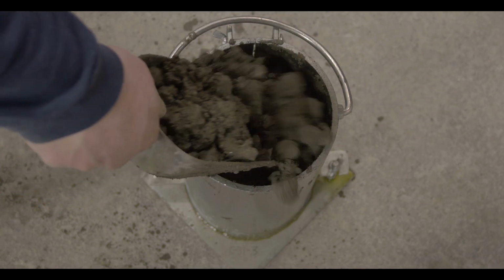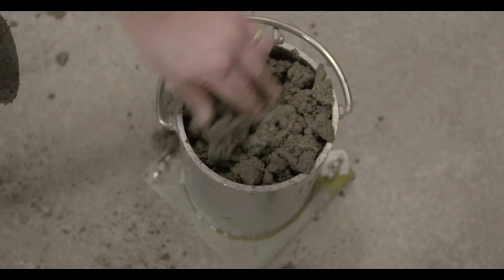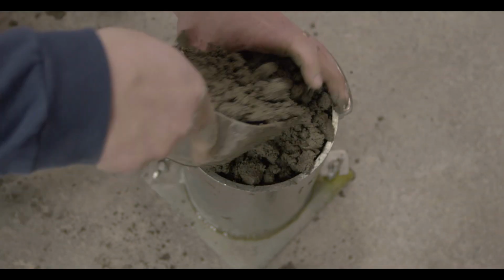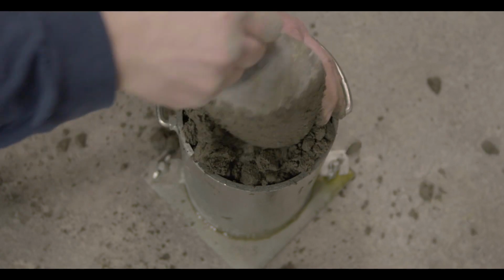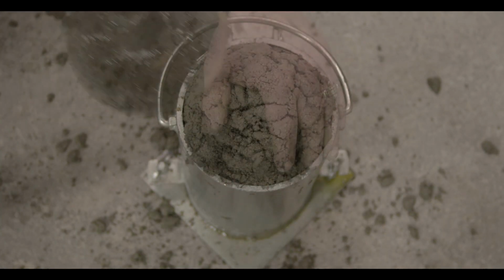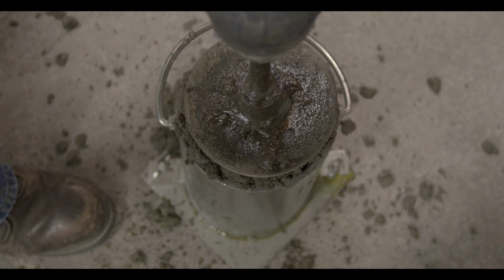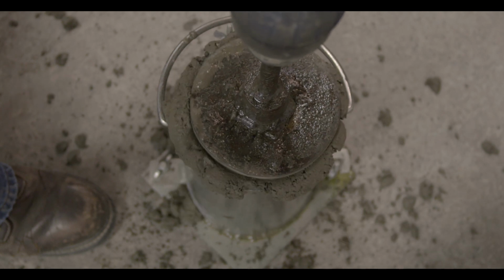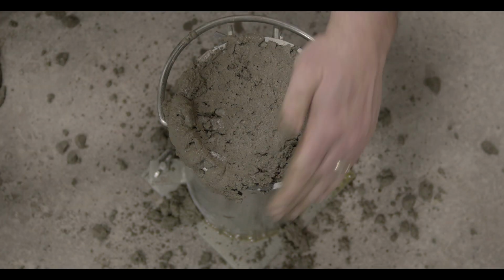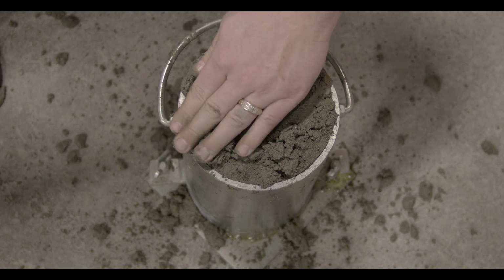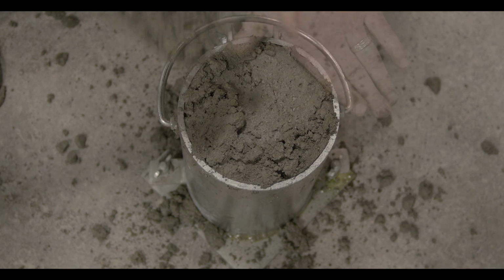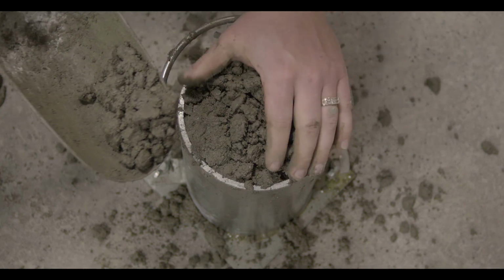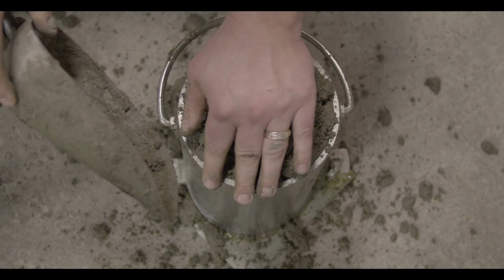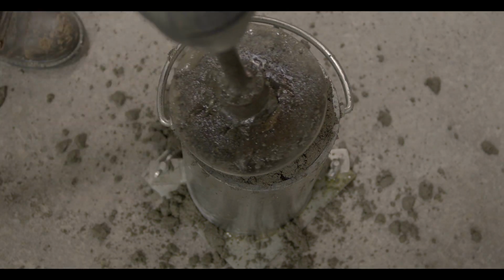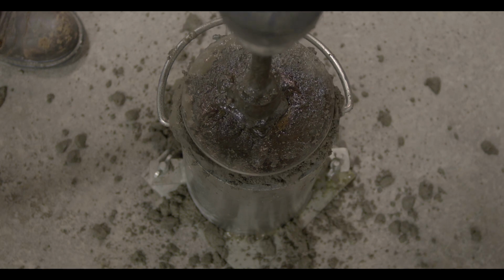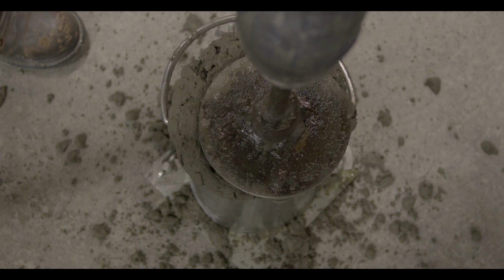For the fourth lift, overfill the mold by mounding the concrete above the top of the mold. Again, place the tamping plate on the loose concrete and consolidate. If the tamping plate consolidates concrete below the top level of the mold, turn off the vibrating hammer. Place additional concrete in the mold so that when consolidated, the concrete can be finished smoothly and level with the top of the mold. Finally, strike off the top of the concrete with the vibrating hammer and tamping plate.